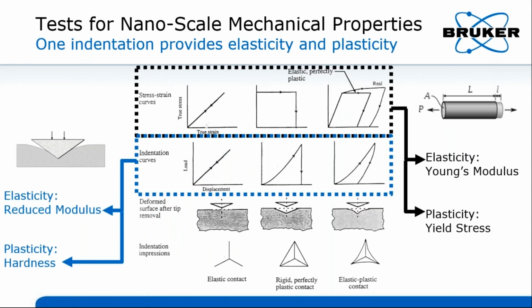Therefore, the concept of one single test for one set of mechanical properties, one is elasticity and the other one is plasticity, is shown here. One biggest difference between nano and the macro test is highly local stress strain can be achieved and highly accurate positioning can be done. With the similar concept of one test for one set of results, we are able to collect one set of mechanical properties from one single nano indentation. The elasticity is reduced modulus, and the plasticity is hardness, corresponding to the Young's modulus and the yield stress that one uniaxial test can provide.